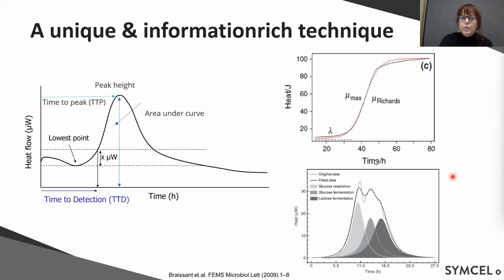So calorimetry is a unique and information-rich technique. Now I just show very few examples here. There could be a lot more that you can do, but very schematically, there are some things that you can very easily analyze. We talked about time to detection. It could be when it rises a certain number over the baseline, and I put X here. It will depend on how your growth curve is, if it's steep or if it's very shallow, where you take your detection point, or if you have a background, a cell background or something, that could be a little different where you put your detection limit. Time to peak you can use otherwise.